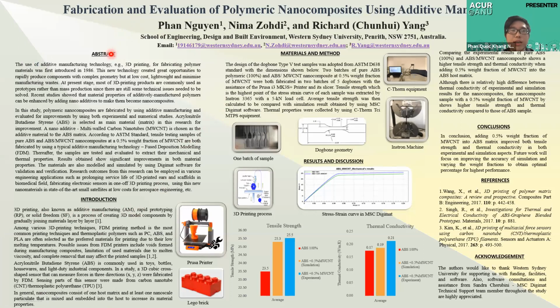In general, my project aims to enhance the properties of acrylonitrile butadiene styrene, or in short ABS, by adding a 0.5% weight fraction of a stronger material, multi-wall carbon nanotube, into the system. The results were evaluated in both simulation and experiment. Eventually, we observed a significant improvement in both tensile strength and thermal conductivity. The outcome of my result can be employed in various engineering fields, such as prolonging the service life of 3D printed ears and scaffolds, creating electronic sensors in just one go, or even building small satellites at low cost for aerospace engineering.